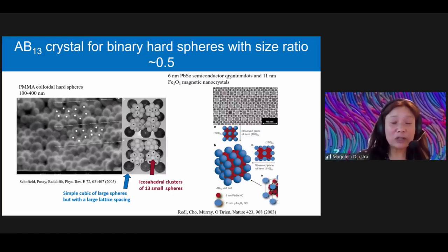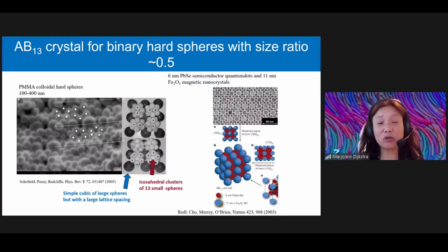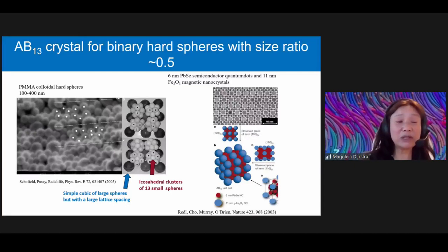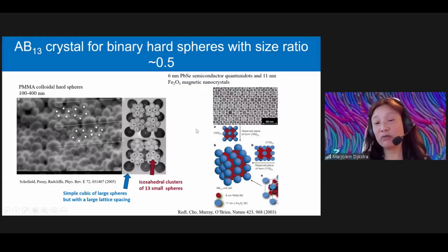And this very exotic lattice consists of a simple cubic lattice of large spheres, which is already peculiar for hard spheres because they usually form a hexagonal lattice. This simple cubic lattice has a very large lattice spacing, in such a way that an icosahedral cluster of 13 small spheres fits in the center of this simple cubic unit cell. Moreover, the icosahedral clusters are rotated by 90 degrees with respect to the neighboring clusters. So the unit cell consists of 8 of these icosahedral clusters with all the big spheres surrounding it. And this lattice has been found in PMMA spheres by Pusey in 2005, but it is also encountered in nanoparticle systems.